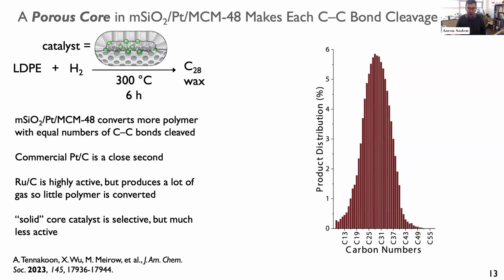So this is really powerful, and it's really powerful because it means we can design the sites, the platinum sites, to give certain behavior, and then we can affect the architecture to control how the processivity occurs, how the polymer exposes itself to the active sites for cleavage. So a second version of this kind of catalyst puts pores in the center. The shape changed because the core changed, but the idea was in the previous catalyst we have dead end pores, and so the polymer goes in and then the product has to come out through the same pores.